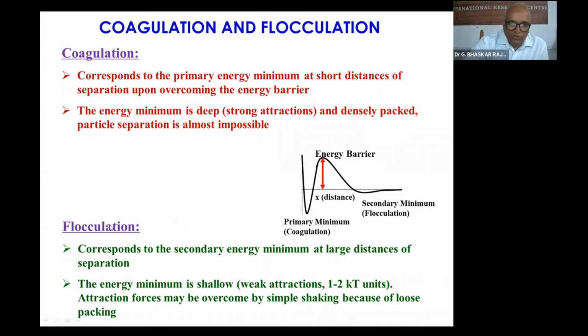The second one is flocculation. Flocculation can be achieved by using flocculants, lengthy molecules which get adsorbed, bind over the entire particle, and then they get flocculated. See here, this again is the DLVO theory. This is the primary minimum, where you can achieve coagulation, and this secondary minimum is where you can achieve flocculation. The energy required for flocculation is very low, whereas at the primary level you need to cross the barrier and need more energy. Flocculation is not that stable, so it can be reversed back to the coagulation condition.